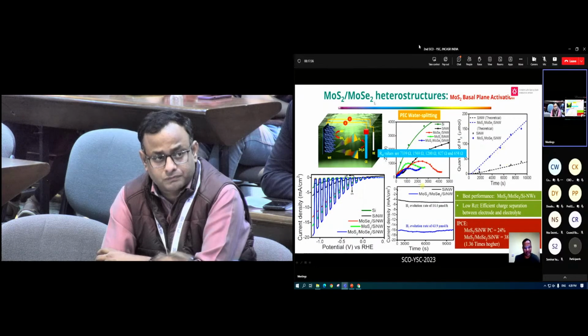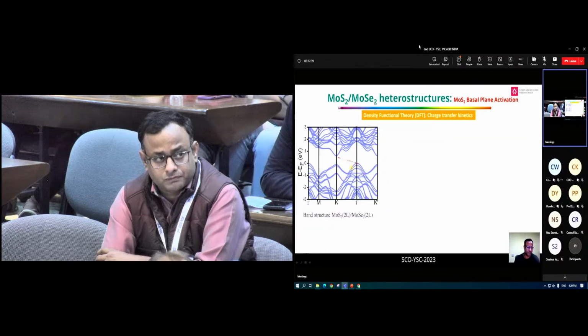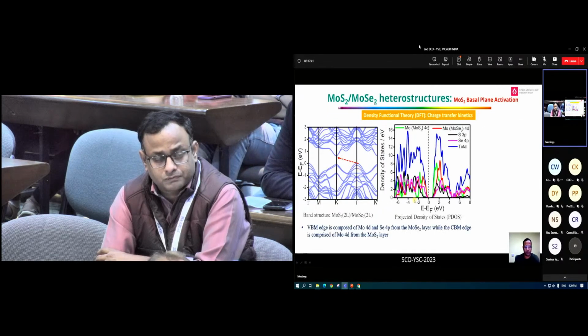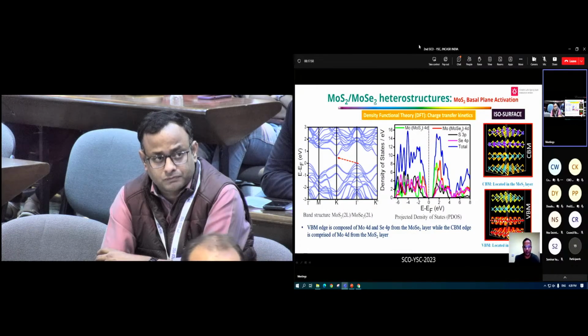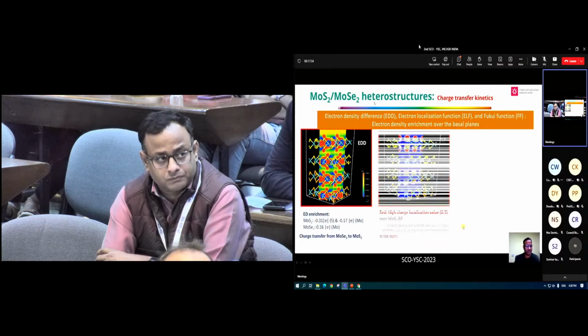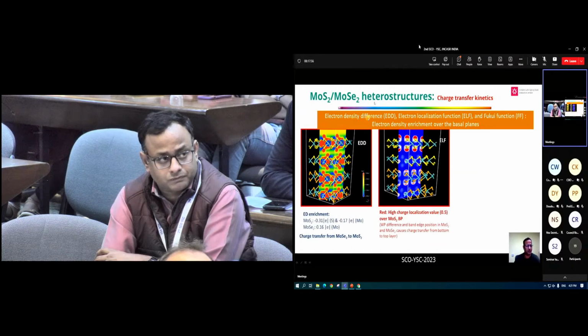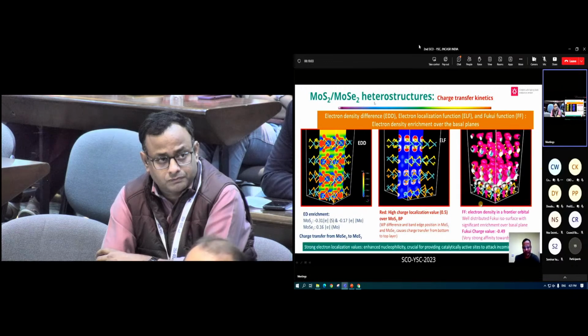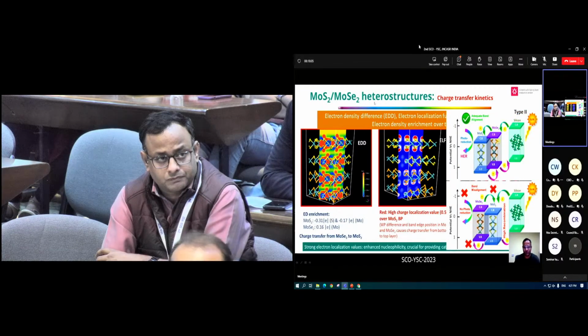Then we tried to understand using DFT. Of course it's an indirect band gap, and when you look at the projected density of states, it says that the valence band is totally dominated by MoSe2, and the conduction band is totally dominated by MoS2. That is similar to what we got from the XPS. Once you look at the electron density difference and electron localization function, it tells you that the complete basal plane is activated once you have these heterostructures. Then we tried to understand their band structure. Once MoS2 is on top, it shows type II band alignment.